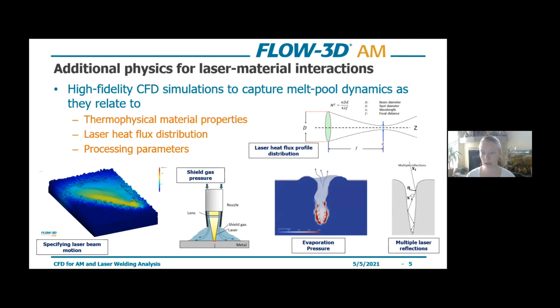And then lastly, multiple laser reflections. We do this via ray tracing, and it's important during keyhole welding where the multiple laser reflections will affect the effective absorption of the material from the laser.